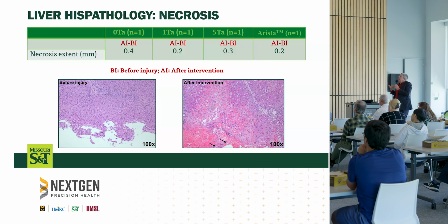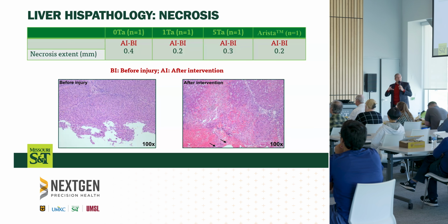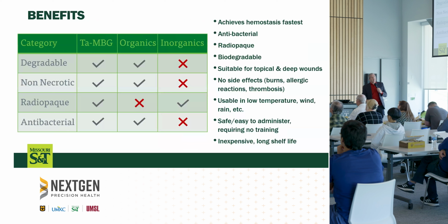Our stuff had a slightly higher necrosis extent, and that's because our material is actually stopping bleeding. It's actually working. The Arista isn't really doing a lot. It's just there, so it's not interfering or intervening in the bleeding process. Our thing is, and that's why it's causing slightly more necrosis than it would do in the Arista situation. So very quickly then, going back to what we talked about if you remember slide 4 at the start, and we looked at all the things that an ideal hemostat should need, we find that our material ticks most of those boxes.